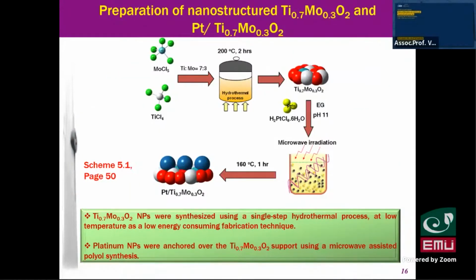When we explored this material, we believe this is the first study we carried out. We apply the hydrothermal process to synthesize titanium 0.7, molybdenum 0.3, O2, using low temperature around 200 degrees C for only 2 hours, with a ratio of 7:3 for titanium and molybdenum.